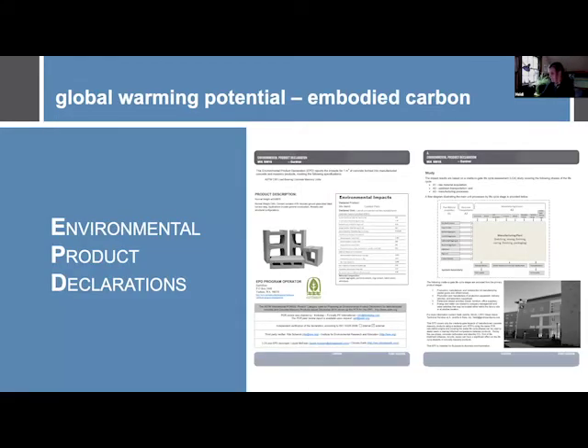So looking at our EPDs, we had environmental product declarations done for every single one of our mix designs. That was about 400 of them, and it was really interesting, some of the things we got from it, like using crushed concrete as an aggregate. We thought we were doing the right thing by having post-consumer recycled content, but actually we found that it brought our global warming potential up, and mostly because of the quality of the aggregate. We had to use more cement. And we weren't saving it from the landfill. It's used as road base, so little things like that we didn't think of.